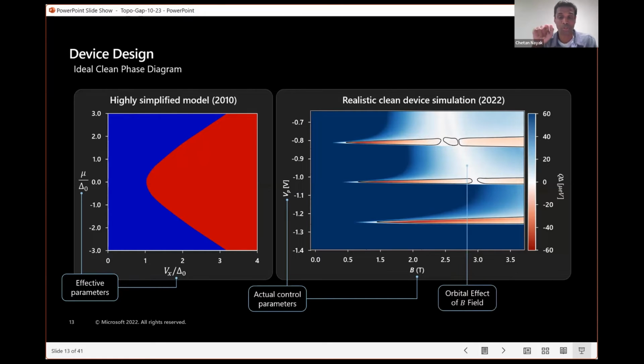Secondly, the wire is not truly one-dimensional, it's quasi-one-dimensional. So actually the magnetic field has, in addition to the Zeeman energy, orbital effects, and the orbital effects suppress the superconductivity, both in the trivial and in the topological phase. They simply suppress how much superconductivity you can induce in the semiconductor. And so what's actually happening here is this is when the magnetic field is large enough to thread half of a flux quantum through the full cross-sectional area of the superconductor-semiconductor sandwich. Okay, so that's extremely bad for superconductivity, and that's why you see what you see here. An important feature of this phase diagram is that actually the lowest subband, meaning when only a single subband is occupied, is highly advantageous for the topological phase.